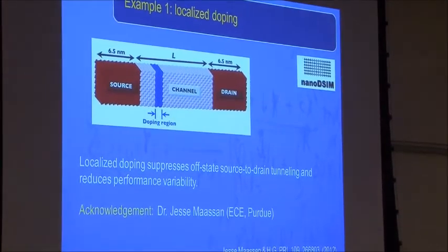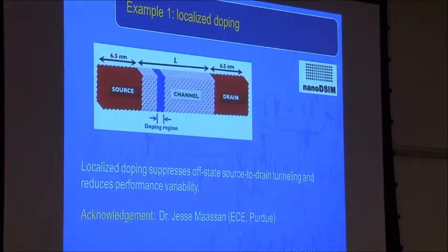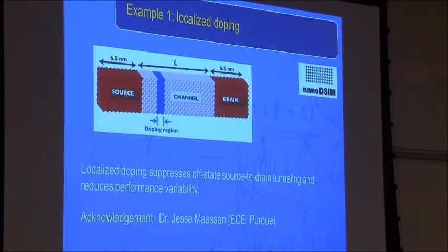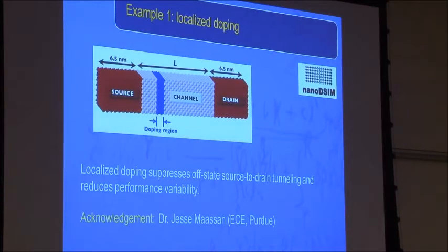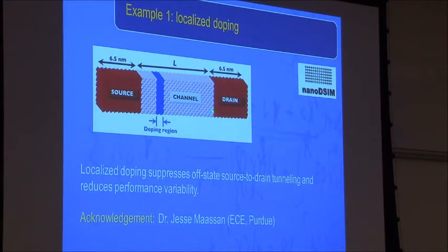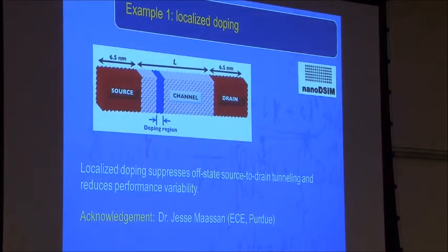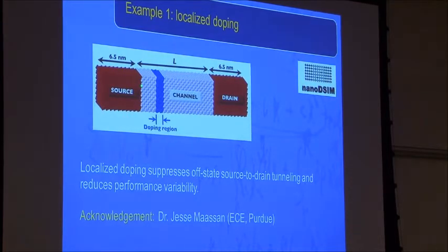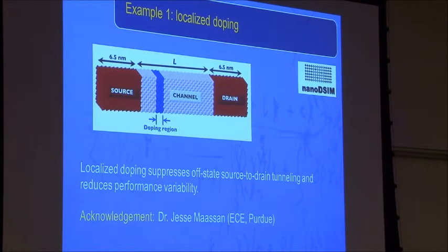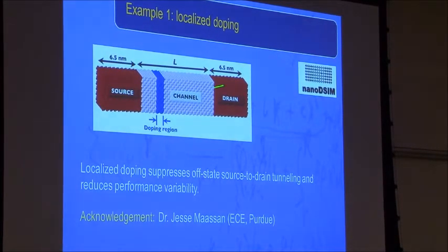So the first example I will give you is done by a PhD student, Jesse Maassan. He is now doing a postdoc at Purdue. And so we were looking at a MOSFET. You have leakage, right? Leakage current goes to the dielectrics through the gate. But that is sort of relieved a little bit by using the high-K material. And there is a source to drain leakage, which seems to be more difficult to deal with. The reason is that when this L is very short, you just have tunneling. So you cannot turn off the transistor. It's over. The electron just tunnels through.